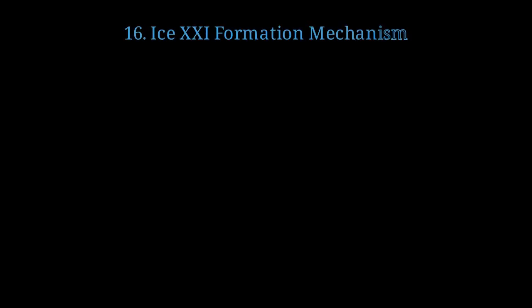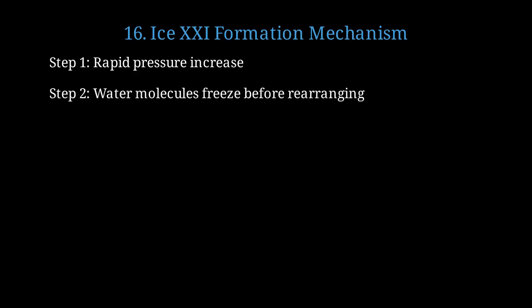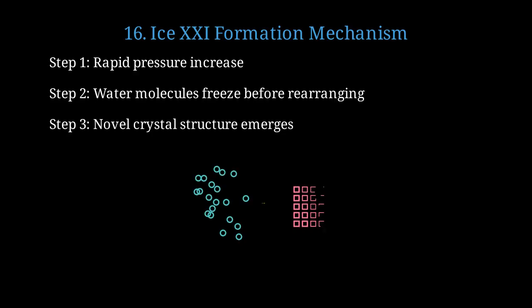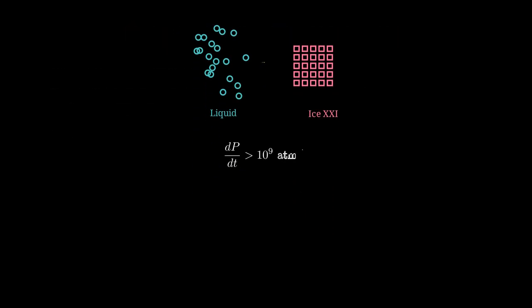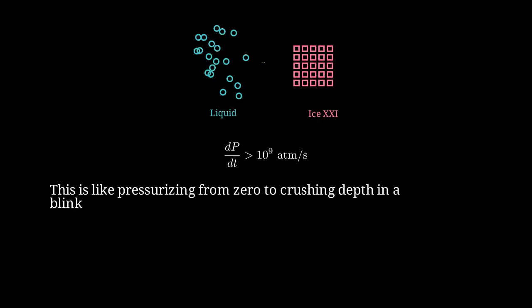Let's understand exactly how Ice 21 forms through ultrafast compression. First, pressure increases extremely rapidly, in less than a millisecond, giving molecules no time to find their normal arrangement. Water molecules freeze in place before they can rearrange into familiar ice structures. This traps them in a completely novel crystal structure that wouldn't form under slow compression. Here we see the transition from disordered liquid water on the left to the ordered Ice 21 crystal structure on the right. The pressure increase rate must exceed 10 to the 9th atmospheres per second to create Ice 21. That's like going from normal pressure to the pressure at the deepest ocean trench in the blink of an eye.